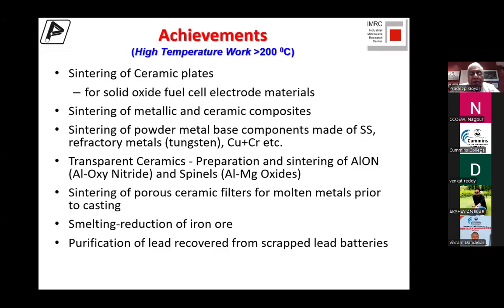Sintering of porous ceramic filters is an extremely viable process. A lot of Japanese, Chinese mills are using this for casting, and so it's a standard process now. Smelting reduction of iron ore is what I'm going to show you a little more. Purification of lead recovered from scrap lead batteries we did for a company that has developed a low temperature lead recovery process by electrolysis. So some of these works we did for many different companies.